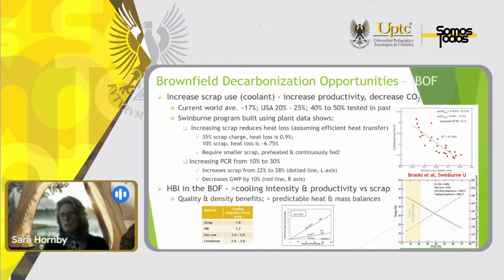The US is using between 20 and 25%, but in actuality, in the past, we've used up to 50%. Now, there's a Swinburne program that was built on plant data, and those are the two graphs on the right-hand side. The top one shows increasing scrap reduces heat loss. So if you move the scrap to 35%, your heat loss is only going to be about 0.9. If you drop the scrap use back to about 10%, you're going to have a heat loss of 6.75-ish.